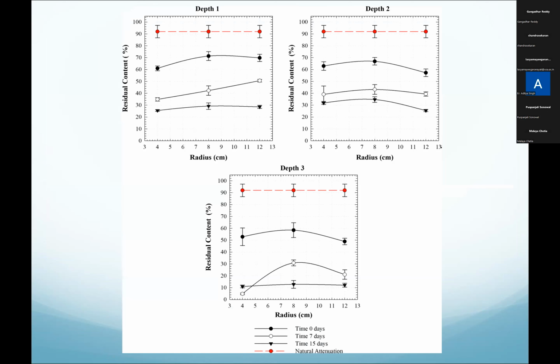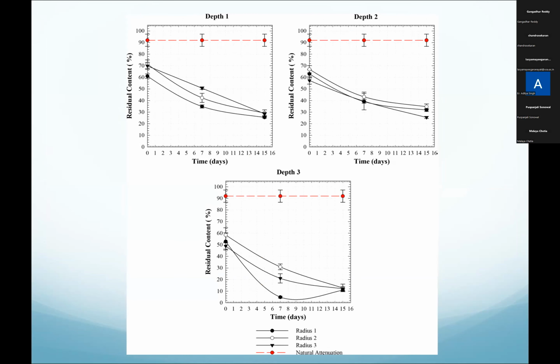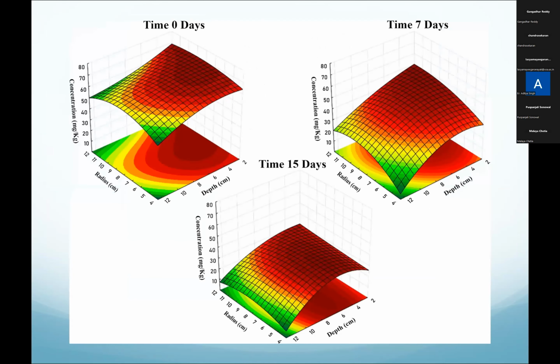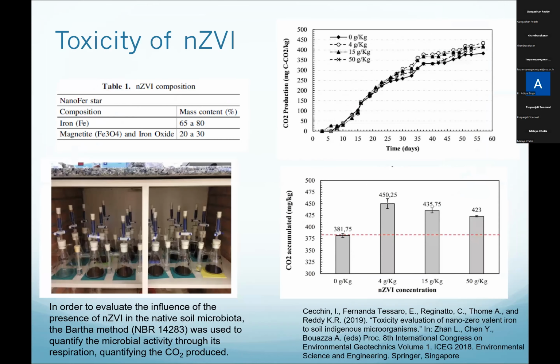and contamination concentrations. So at different depths and at different radial distances, you can plot all the data and analyze what is happening to the contamination at different depths, and also what is happening to the iron distribution. And you can create 3D plots to understand the contamination degradation and the iron transport. And toxicity is a big issue.